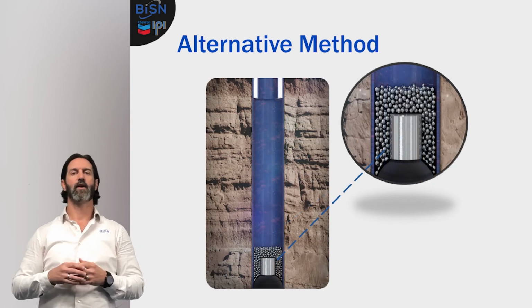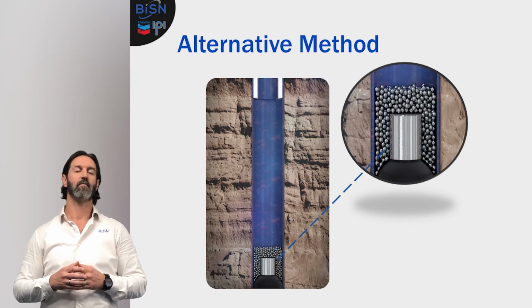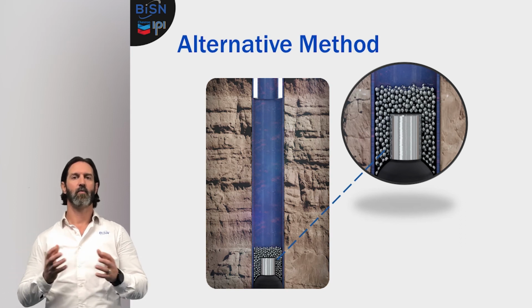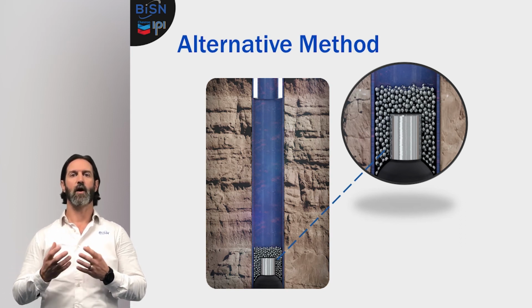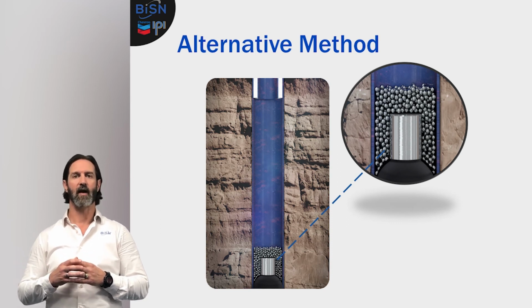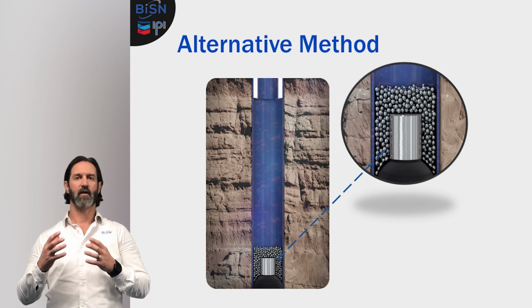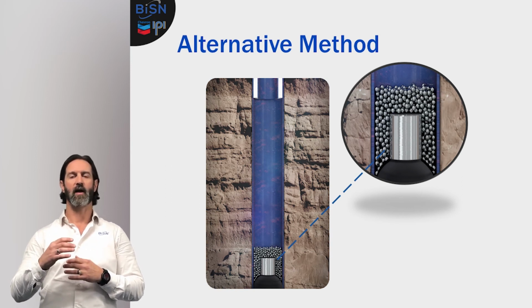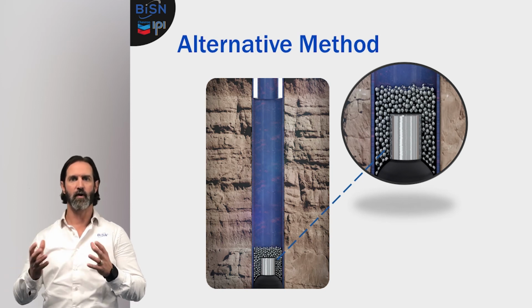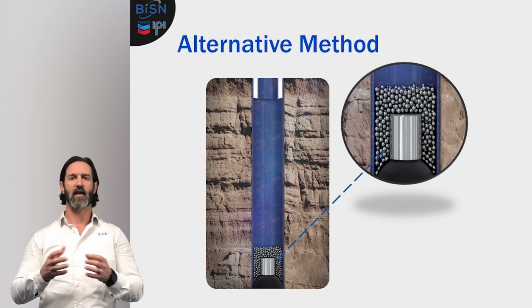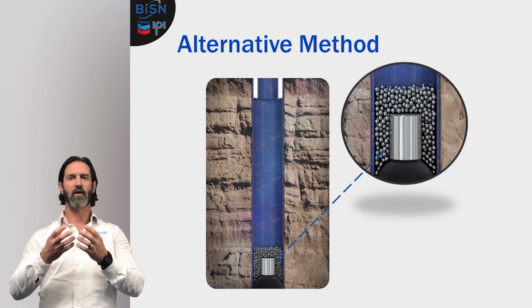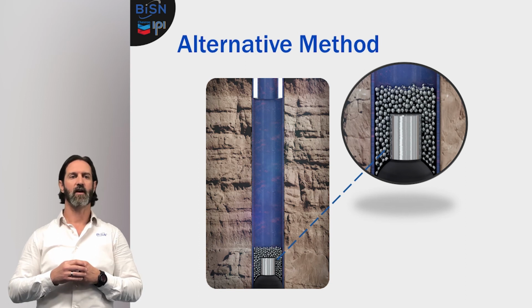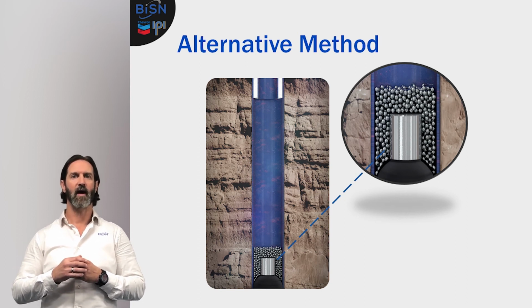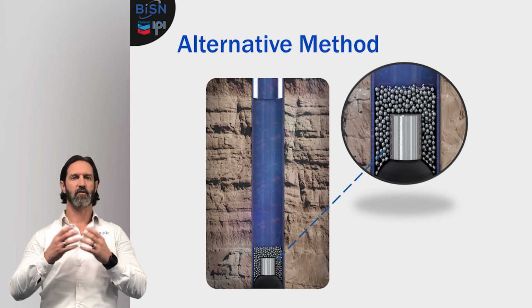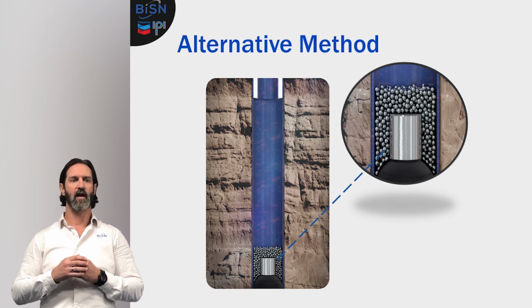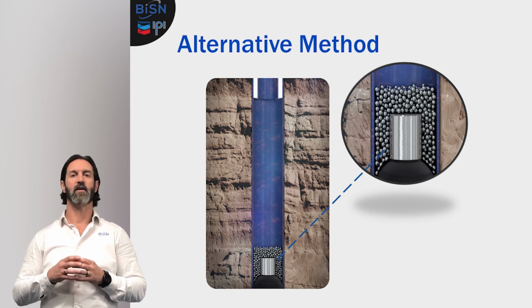All right, so the window has been cut. The IPI packer has been set inside that window, as you've seen. The next step was to take bismuth alloy beads and drop them down the well on top of the IPI packer. So this does a few things. One, it fills in the void. The IPI packer has quite a long fishing neck, so what we want to do is maximize the alloy we send down in the plug to make sure it's all forming the plug and we don't lose any of that down around the fishing neck of the IPI packer. Second, it protects the IPI packer. Having that standoff there ensures that none of this liquid alloy, which is quite hot, is going to get down to the element and potentially damage the element itself.